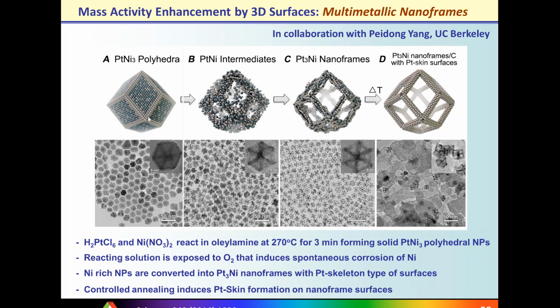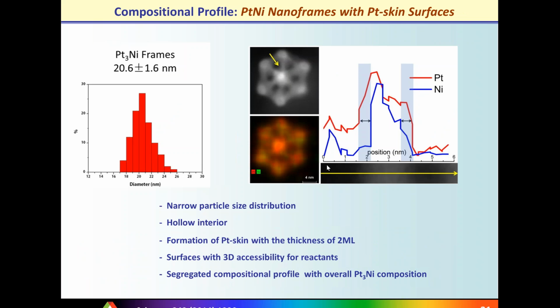So platinum nickel 3 nanoparticles were intentionally exposed to an oxygen-rich atmosphere, which induced so-called spontaneous corrosion, which led to that open frame structure. And ultimately, going from here to this type of particle with multi-layer skin surfaces, we spent a significant amount of time to actually be able to control and to tune surface composition in such a way that, once we start looking into those structural characterizations, we could confirm the thickness of the platinum layer was at least 2 atomic layers, and with very high nickel content inside of each frame. So the thickness of each frame was around 2 nanometers, and basically we are looking at a nicely ordered 3-dimensional network of nanowires, nicely assembled into those nanoframes.